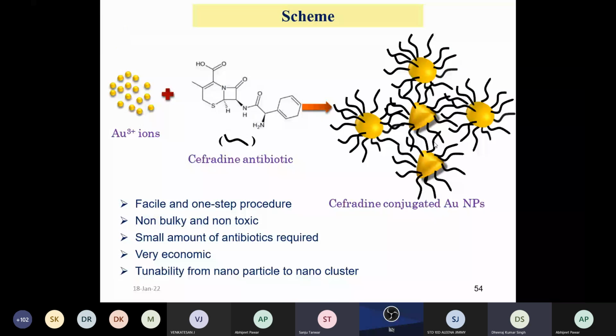We took HAuCl4, chloroauric acid, from the market; it is the metal salt. In HAuCl4, gold has a +3 charge, because H is +1 and Cl4 is -4. In HAuCl4 we simply mixed the antibiotic molecule. This is the cepradine antibiotic molecule, and in it this region is the beta-lactam. In this chloroauric acid aqueous solution, stirred on a magnetic stirrer for a few minutes, directly without mixing any other element, you have synthesized the gold nanomaterial.